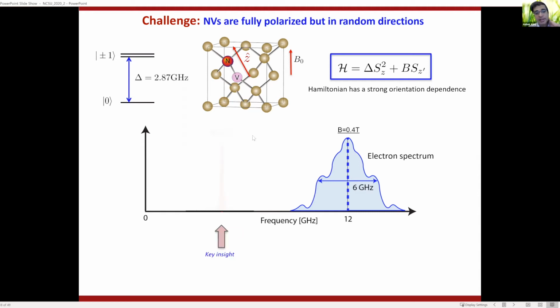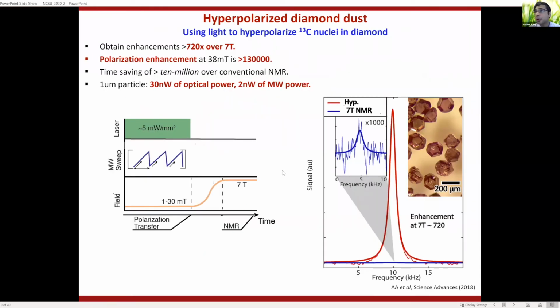And it turns out that that is actually possible if you just operate at a slightly different magnetic field. And I'll show you why, but the insight is to operate at a slightly weaker magnetic field, in which case the broadening is not so much. But we came up with a very simple protocol that achieves this. And I just want to walk you through the protocol and show you the results here on the right.